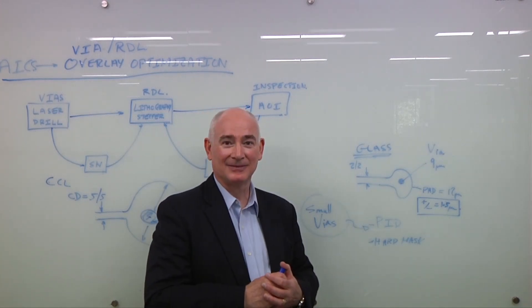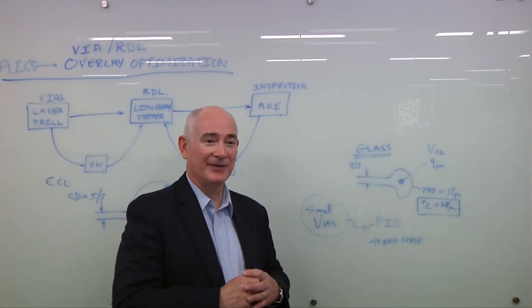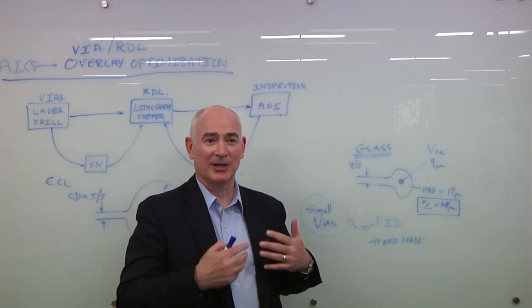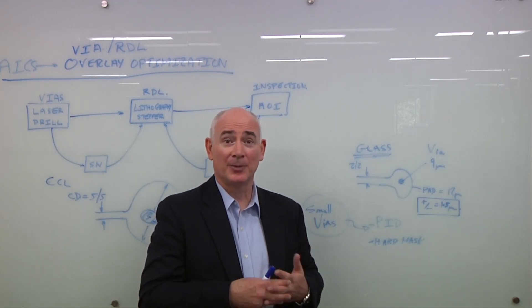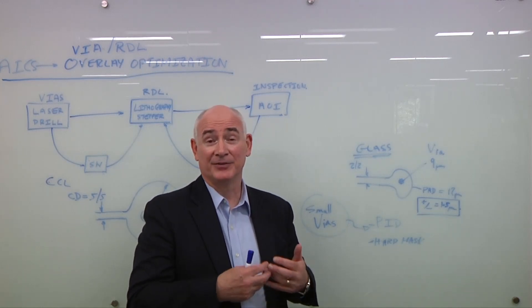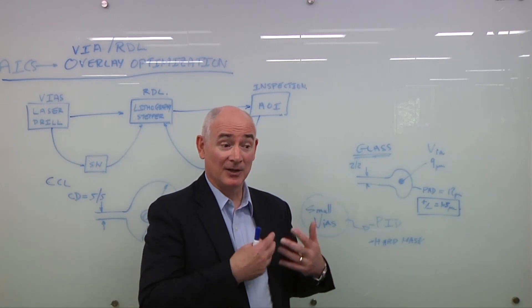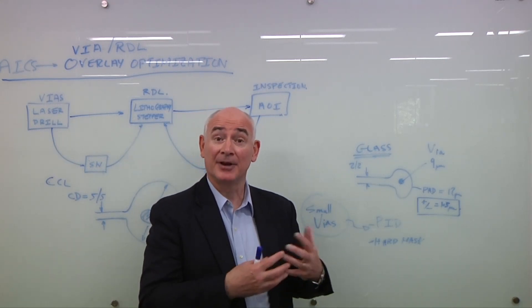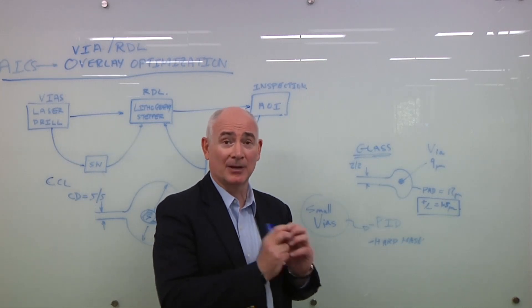So what's missing out of this? So we've got the glass. We understand how that's going to work. What is going to make this work in high-volume manufacturing? Yes. In fact, what's going to happen is some of the actual other processes will change. So you're familiar with electroless copper plating. It will now become more electroplating and have different types of seed materials. So you've gone from electroless seed into now PVD type of seed. So again, front-end type of capability.